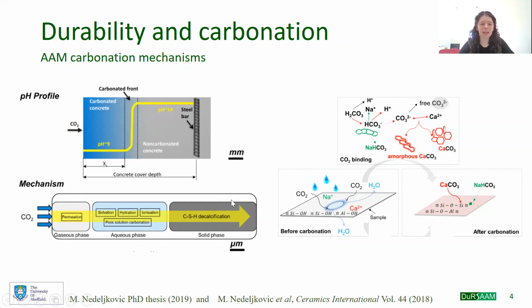But for alkali-activated materials, carbonation can also be an issue because if the C-S-H and N-A-S-H phases are decalcified, they can lower the mechanical properties of the materials, which we want to avoid.